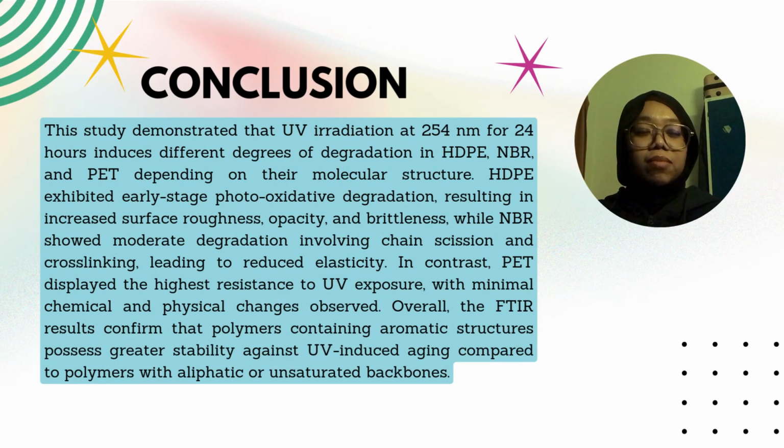This study demonstrated that UV irradiation at 254 nanometers for 24 hours induced different degrees of degradation in HDPE, NBR, and PET depending on their molecular structure.